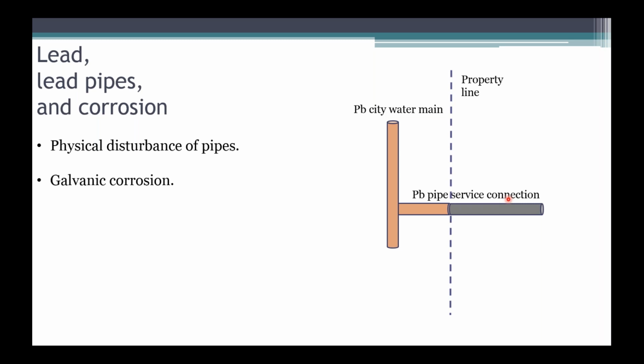And even when lead service lines are replaced, other factors can continue to contribute to the potential for lead to enter the tap water. The physical disturbance of actually replacing distribution lines can disrupt the scale layers on the insides of the pipes and potentially mobilize lead into the drinking water. Junctions where two different metals come into contact with each other can be a site where galvanic corrosion occurs, and I'll talk more about galvanic corrosion in a few minutes.